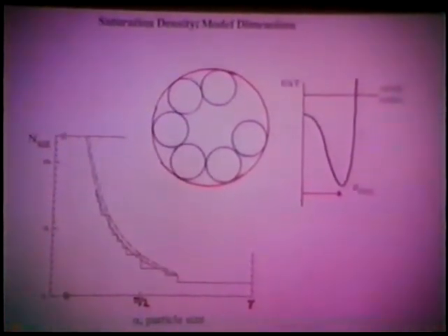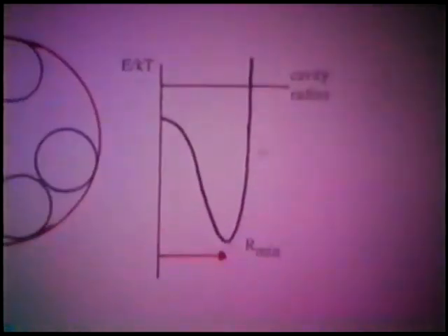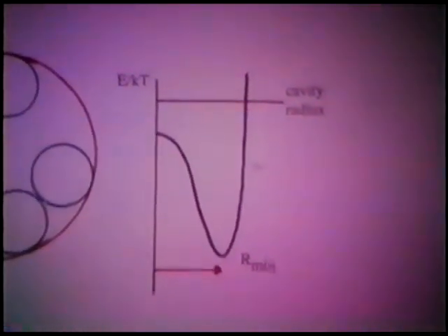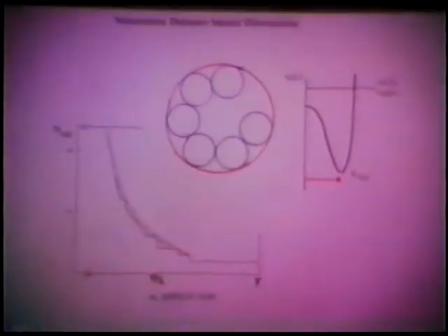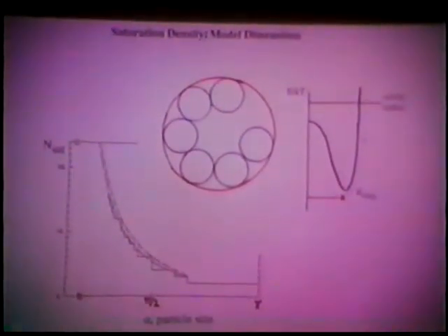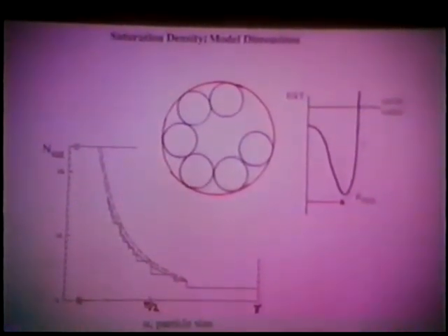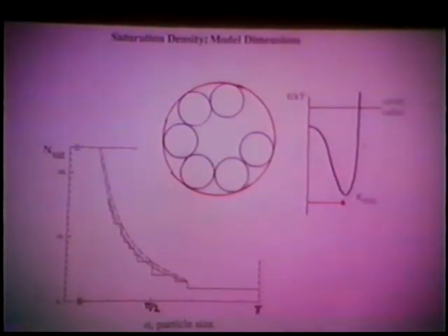Instead of doing that, what I could do is use data on the saturation capacity of various zeolite cavities and use that to determine the size of the absorbing surface. It's a rather difficult problem to calculate the number of small spheres that could be fit just right on the spherical surface.